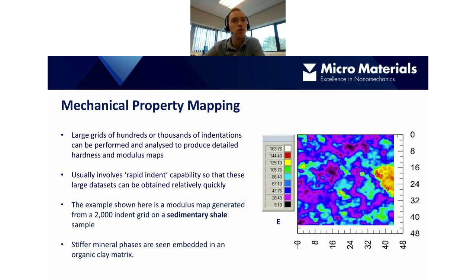Mechanical property mapping is another common application. This is where we perform a large number of indents very quickly over a given area of the sample. The area is typically tens of microns. So in this particular example, we've used the nanotest to perform an indent grid containing around 2,000 indents on a sedimentary shale sample. Once we've analyzed the data, we can take the hardness and modulus values and plot them into a 2D or 3D color map, so we can visualize the variation in hardness or modulus over this area.